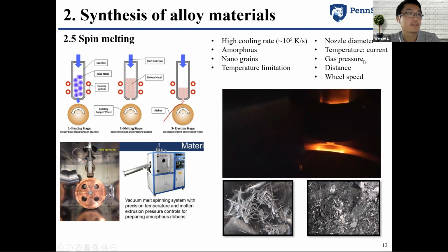So how the ribbon materials can be fabricated depends on a couple of parameters, including the nozzle diameter, the temperature, which is basically controlled by how large a current you apply, the gas pressure, and the distance between the crucible and the wheel speed. This is one good example and one bad example of what happens when you modify those parameters. This is a good one where you can get nice and narrow ribbons. This is a bad one. Something goes wrong, and you get a chunk type of material, which is not good for spin melting.